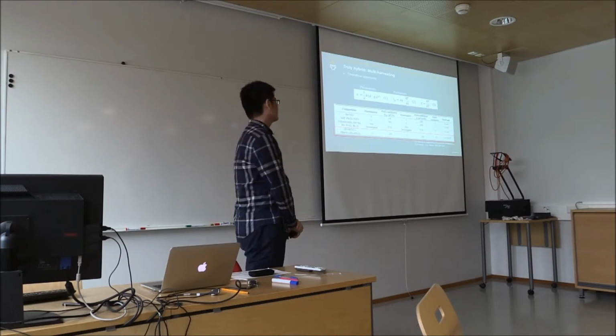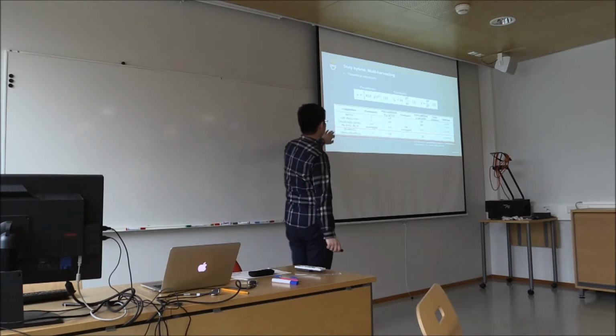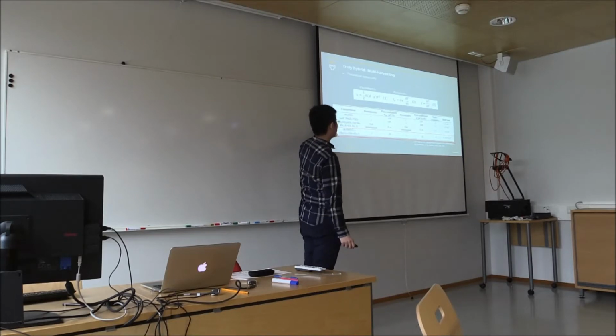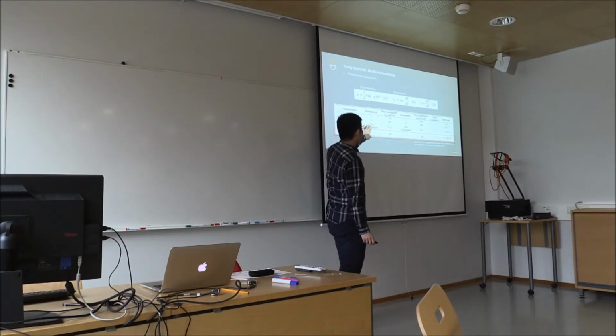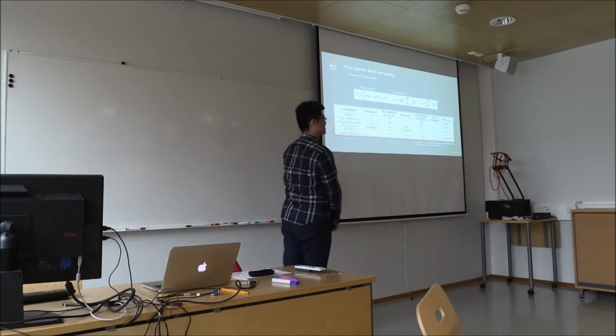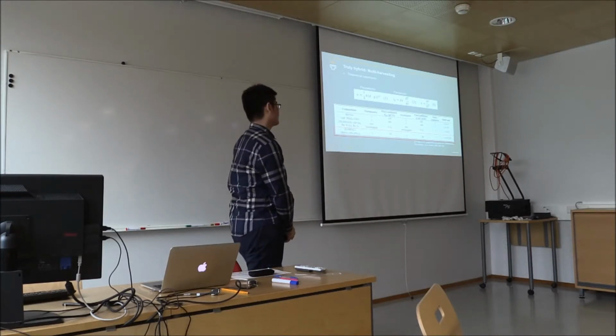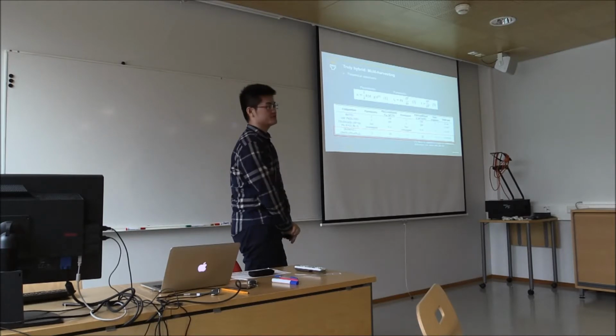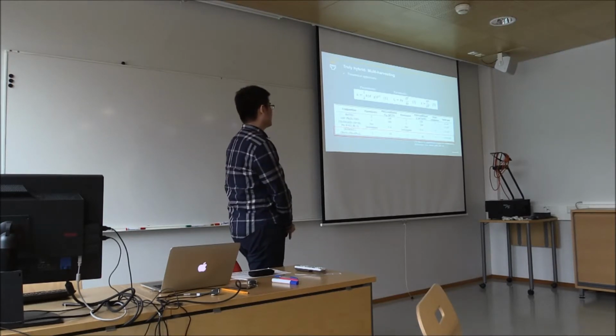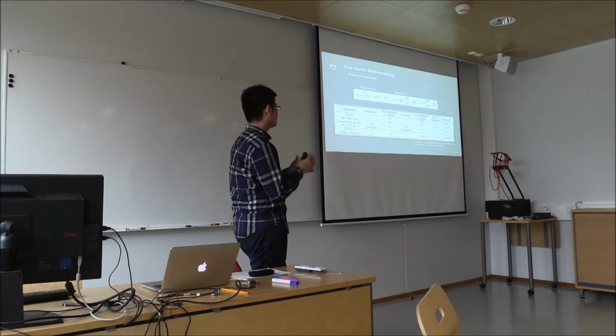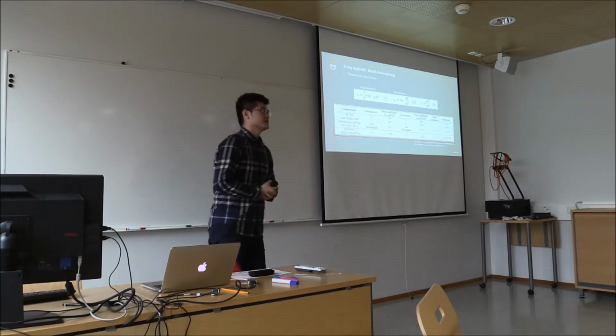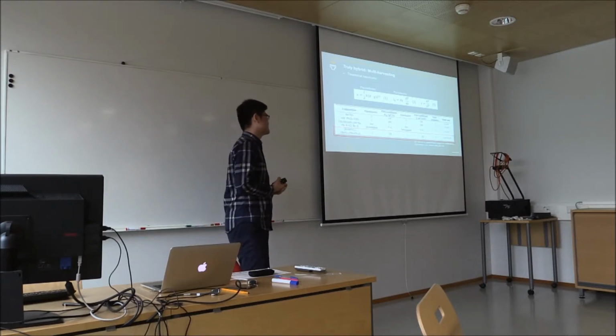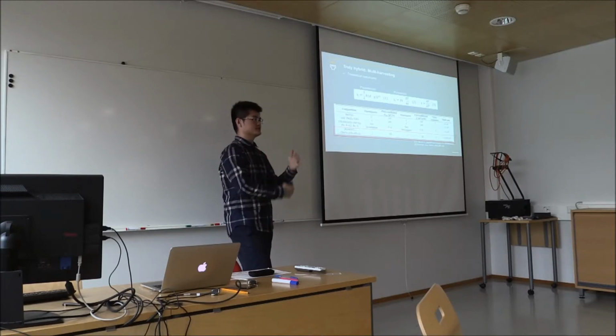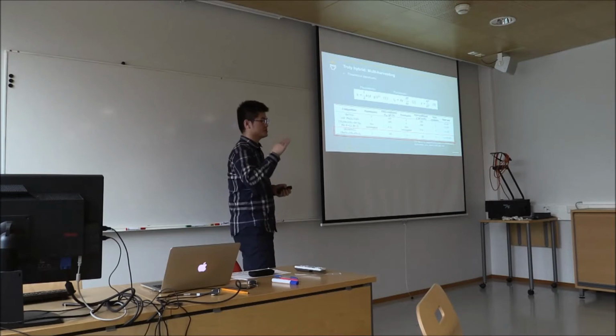We can't use them for visible or sunlight harvesting. And for this one, the band gap is good, but actually it is not well investigated. It's controversial. People don't understand now whether it's a real ferroelectric material, and it sometimes can exhibit some piezoelectric effect, but people are worried that it's just because of the charges accumulated on surfaces. It's not the real internal ferroelectric domain switching.